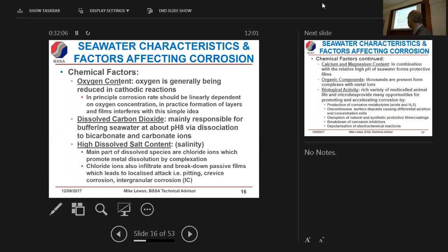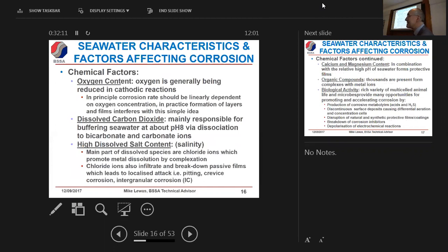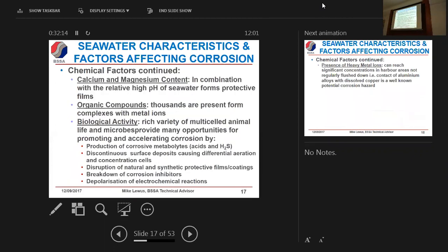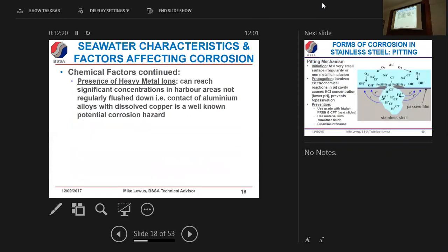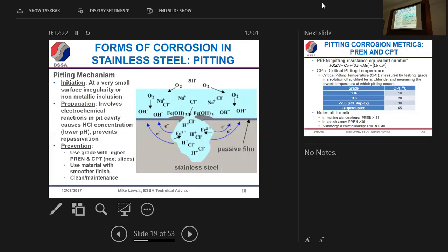Chemical factors, mentioned that, high dissolved salt. The thing about chloride is it's a bit of an enemy of most of the naturally passivating metals, whether it's stainless steel, aluminium, or titanium. Unfortunately, it does infiltrate the structure of the passive layer, and the complexing that occurs as a result causes the passive layer to break down. And as a consequence of that, we get certain mechanisms occurring in stainless steel.